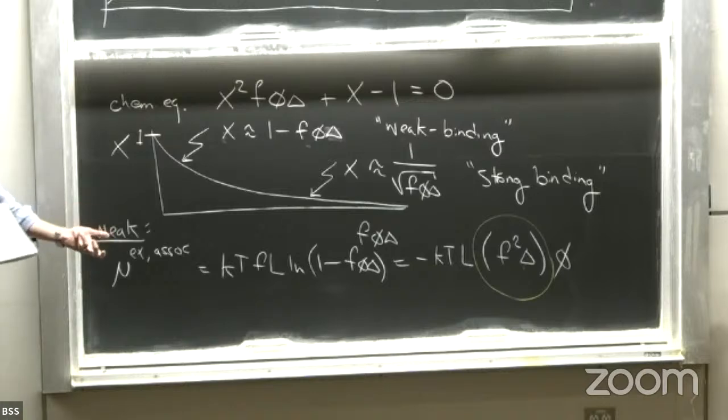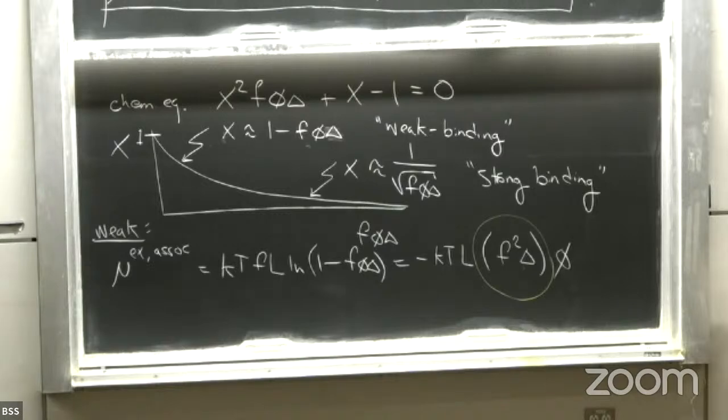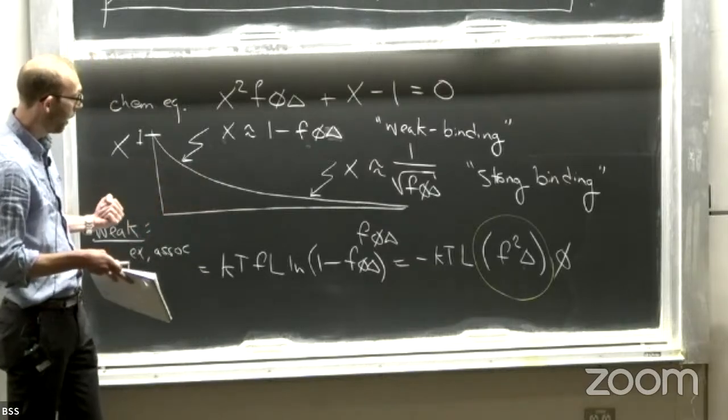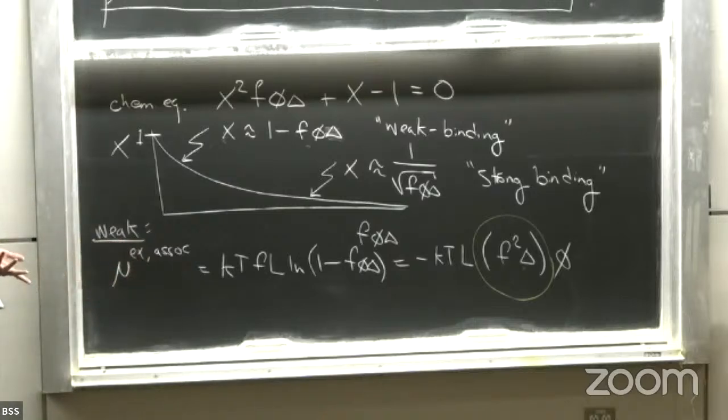we have some binding sites, some monomers have binding sites, other ones don't. We have directional one-to-one interactions. As long as you have relatively weak interactions, your phase behavior should be indistinguishable from that of a system where you just had isotropic pairwise interactions.